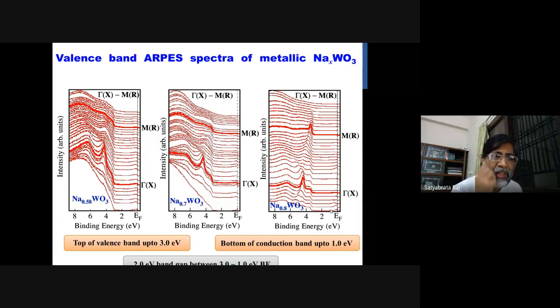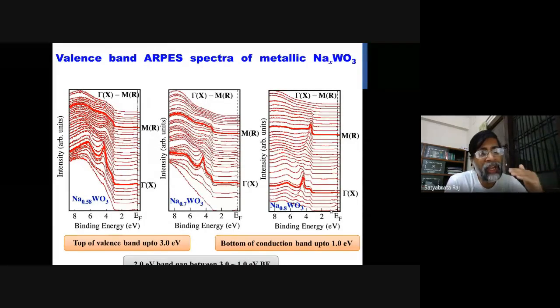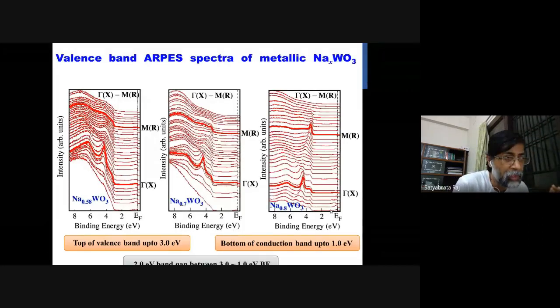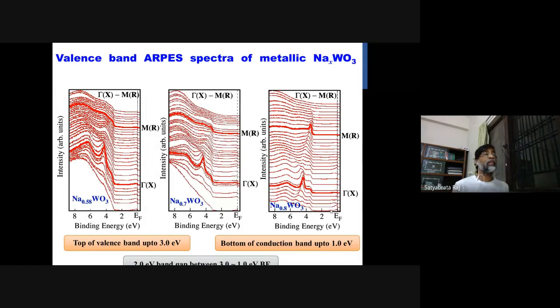As I have already explained, if you put sodium, the sodium 3s goes to the 5d and the system becomes metallic, and if you put more sodium, more electrons will go to 5d and the EF will slowly go up. That is according to the rigid band model. But we are not sure whether the rigid band model is applicable to sodium tungsten bronze or not. People say that the rigid band model can be applied, but that is just an assumption, but we would like to prove whether rigid band is a failure or a success,